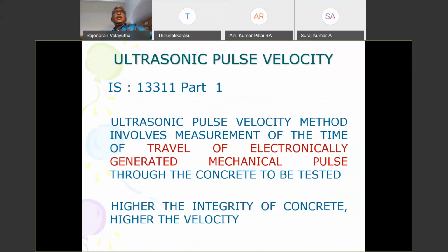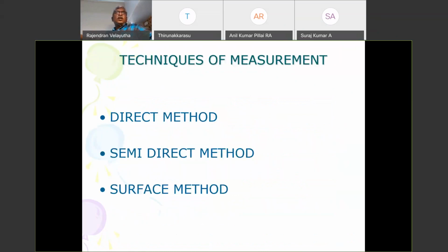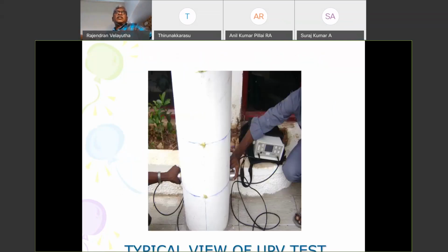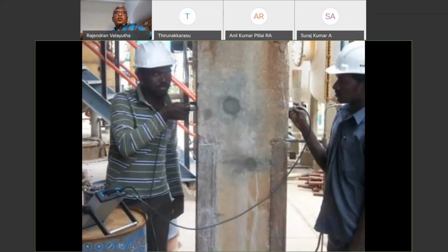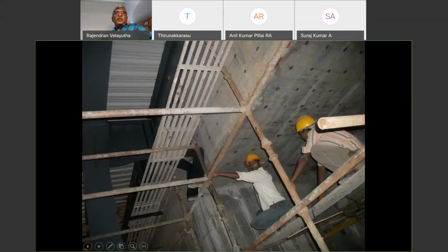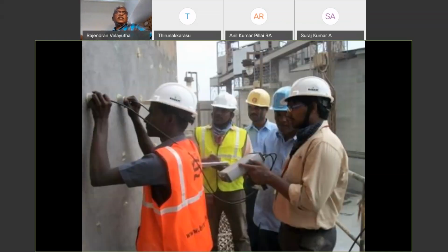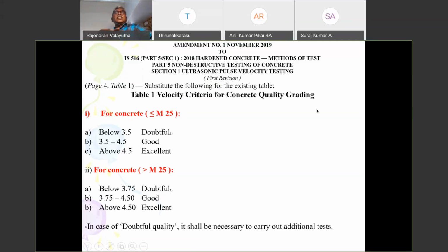As far as the ultrasonic pulse velocity is concerned, earlier we had a different code, but now the code has come into the picture with a little more stringent quality. We all know that it can be done by direct, semi-direct or surface method. In the direct method, the two probes are kept right opposite each other. In the indirect method, one probe you keep here, the other somewhere there, and then you use the Pythagoras theorem to calculate the hypotenuse, and that hypotenuse we take as the path length, and then we calculate the velocity. This is a surface method where you keep both the transducers on the surface. As long as it was there in IS 13311 Part 1, we never had an issue.